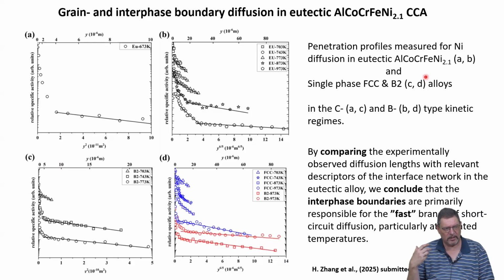So we measure grain boundary diffusivities directly. We basically assume that we measure the interface boundary diffusion also directly in C-type regimes in the eutectic system. And from the data we gather, we can confirm that this is correct, because interface diffusion is faster than grain boundary diffusion. So it means these C-type kinetic regime conditions to solve the diffusion equation are even better fulfilled in this case.